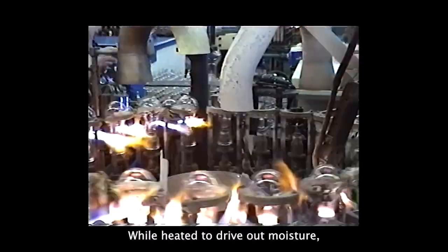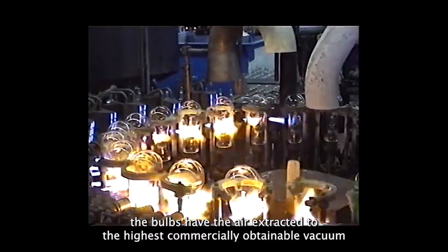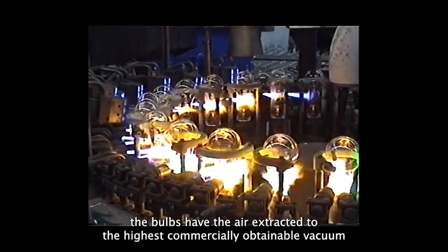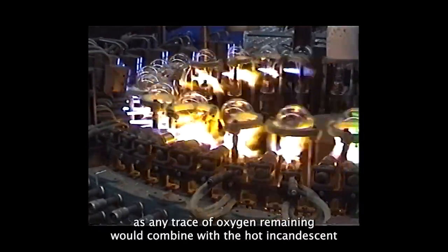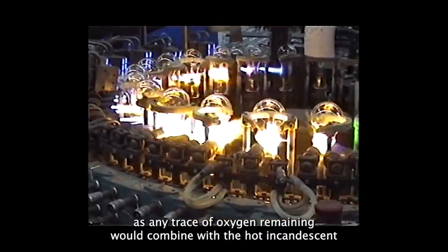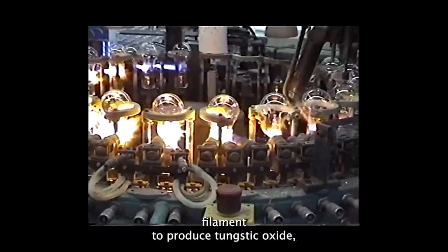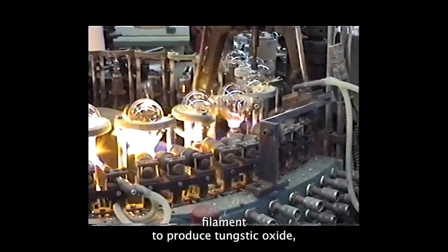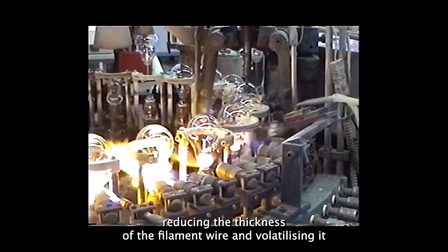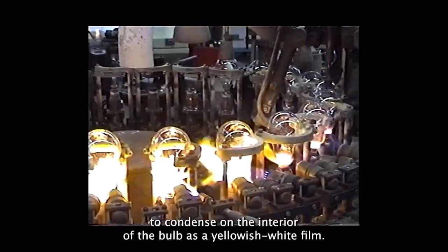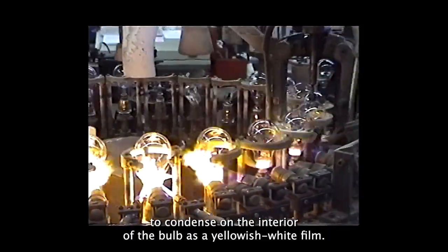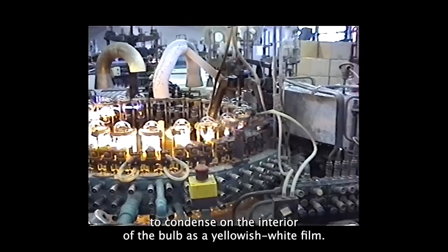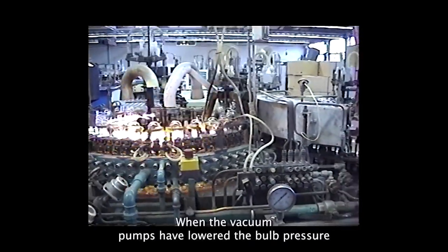While heated to drive out moisture, the bulbs have the air extracted to the highest commercially obtainable vacuum, as any trace of oxygen remaining would combine with the hot incandescent filament to produce tungstic oxide, reducing the thickness of the filament wire and volatilizing it to condense on the interior of the bulb as a yellowish white film.